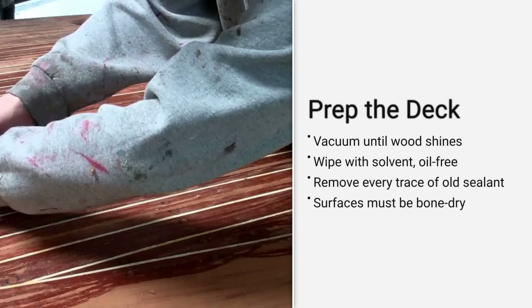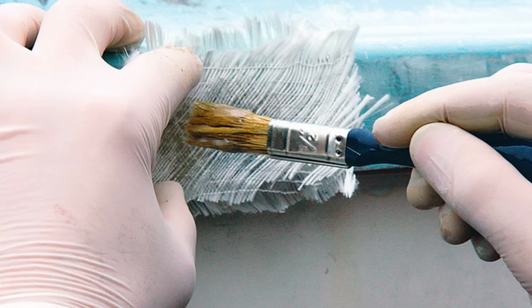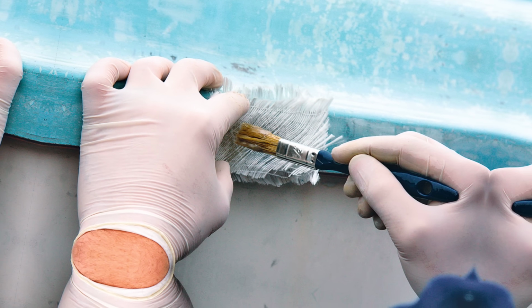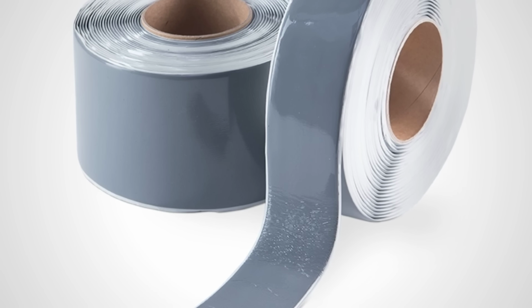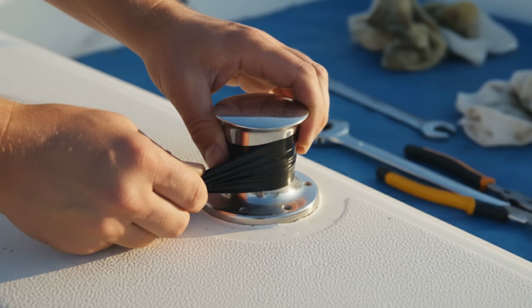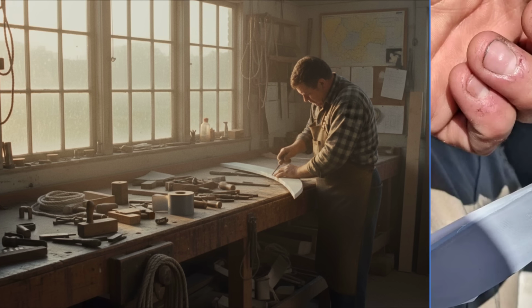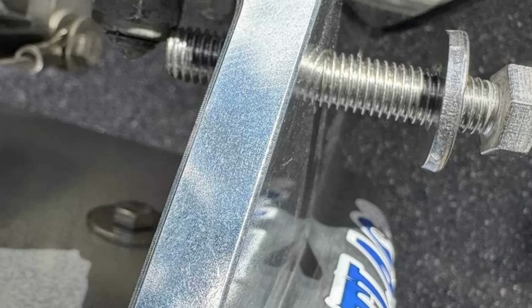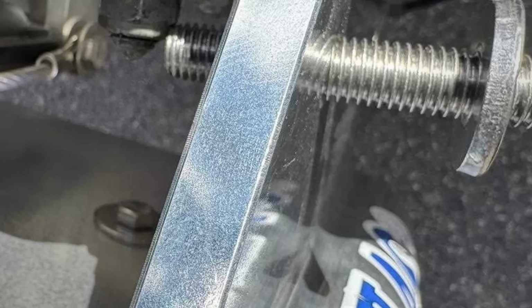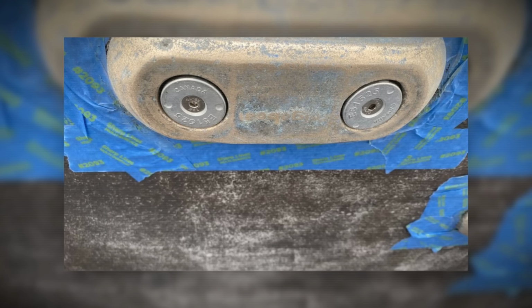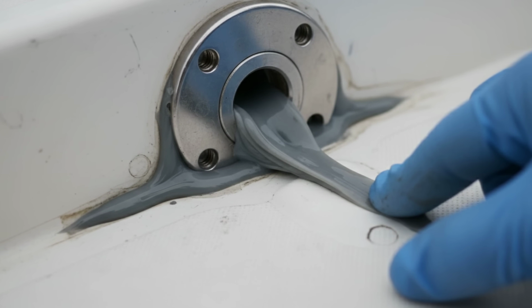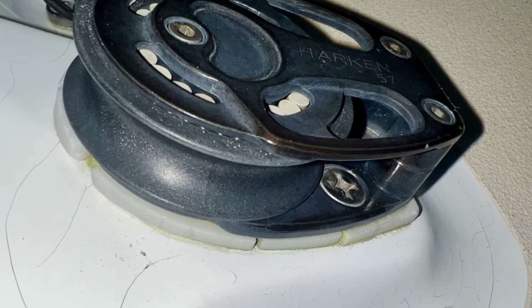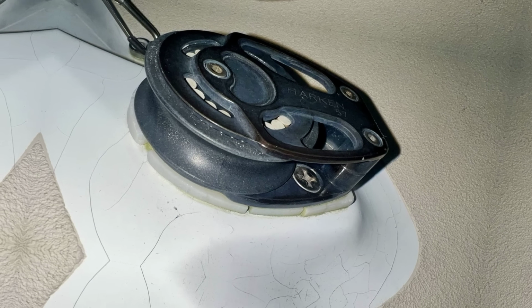Next, clean every surface, no dust, no oil, no old sealant. If there is any trace of silicone, grind it out until you hit bright, raw laminate. Now take a strip of gray butyl tape, about as thick as a pencil, and wrap it around the base of the fitting. Overlap the ends, do not stretch it thin. Set the hardware in place, lining up the bolts. As you tighten the nuts, watch for that slow, deliberate bulge of butyl squeezing out from under the flange. That is the sign you have a true gasket, not a glue joint, not a chemical weld, but a living, flexible seal that will move with the deck for years.